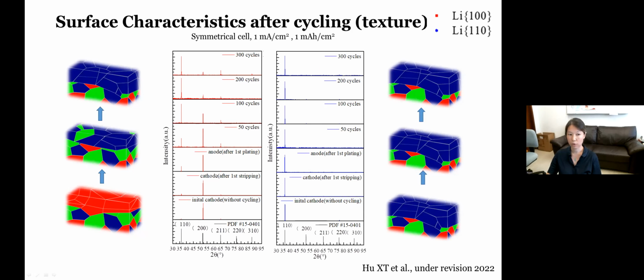And this is the cathode, which is stripped in the first cycle. And this is the anode side, also in the first cycle, which gets plated. And for the lithium 100 sample, you see there's a bit of other intensities coming off, even at the end of first cycle. And this becomes more obvious if you cycle on. And at the end of the 300 cycles, you see the dominant diffraction become the 110 instead of the 200.